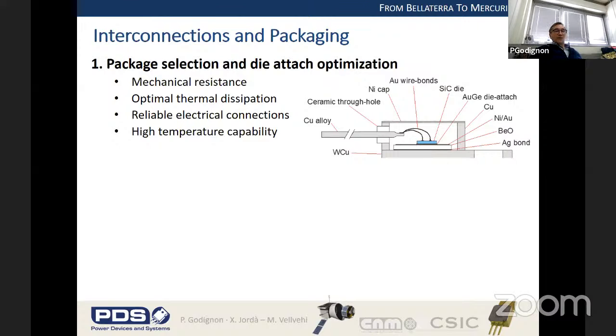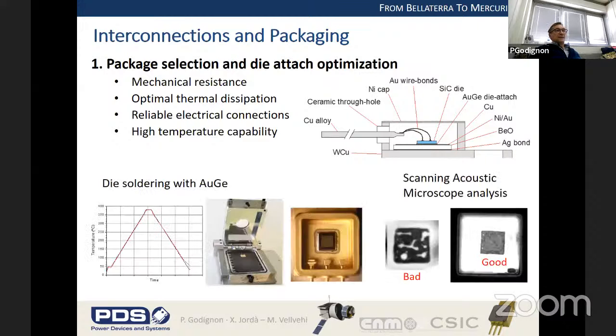So in the case of the device, the packaging has the same constraint as the die. So a very good mechanical resistance, a good thermal dissipation, a reliable electrical connection, and especially high temperature capability. So for that, we again develop a specific package for this component, starting with the backside soldering. So we have to stick the die on the base plate. And for this, we use solder alloy.